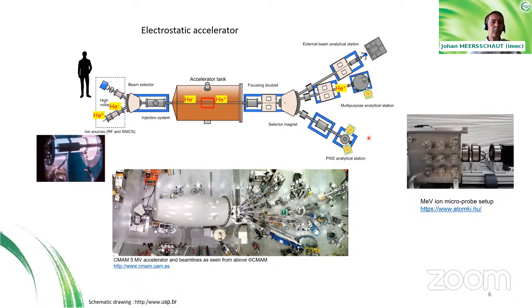with a sample. So on the one hand, much of the effort goes into the installation of the accelerator, but on the other hand, also much work is done to optimize the end stations, to optimize the experiment and investigate the samples. And the different laboratories within Europe are each of them specializing in one specific experimental geometry or detection system to optimize a specific property of detection. And as you see here on the right, this is a microprobe setup, which is, for example, hosted in Atomki in Hungary, and it allows you to define a beam spot onto the sample of the order of submicrometers.